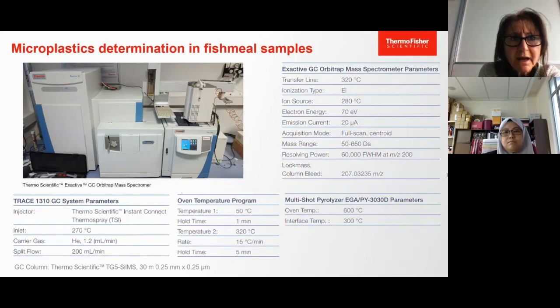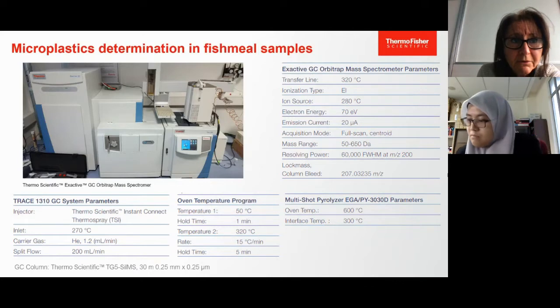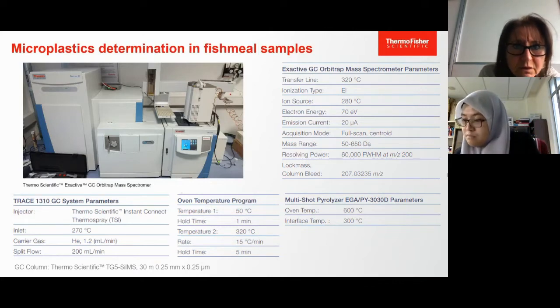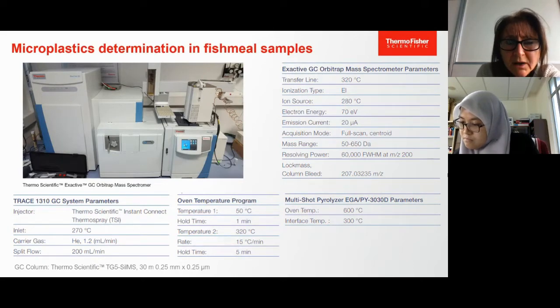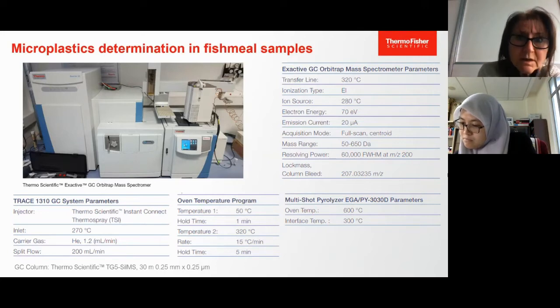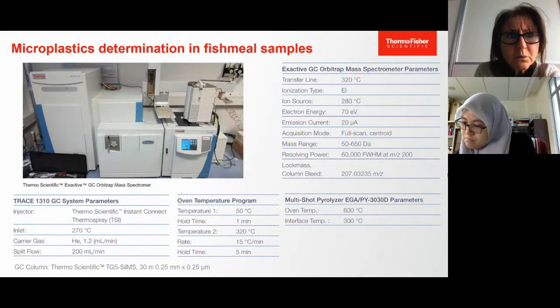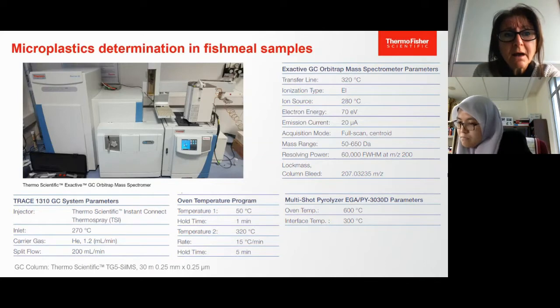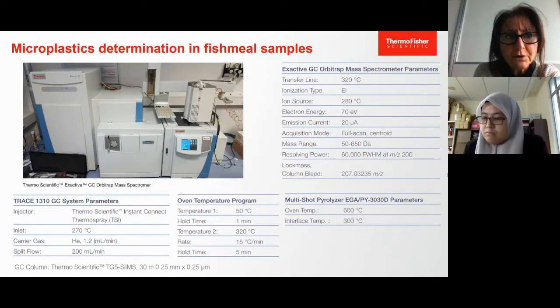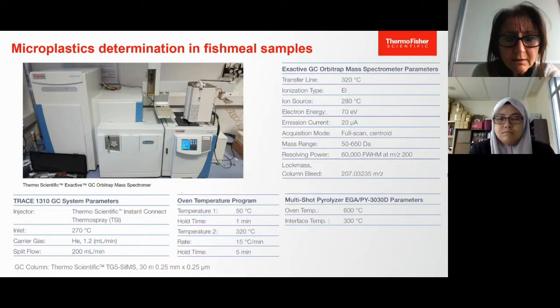The high-resolution MS detection offers enhanced selectivity that facilitates the detection and quantification of low levels of compounds against a complex chemical background. In this slide, you can see the conditions used for the characterization of plastic polymers, as well as for the quantitative determination in fish meal samples. The Orbitrap acquisition was performed in full scan mode from 50 to 650 m/z. And in this way, the method setup is really very easy, at a resolution of 60,000 for the Orbitrap. This study was conducted on the Orbitrap Exactive GC-MS system, as shown in the picture.